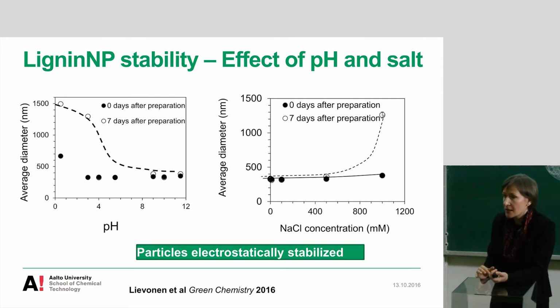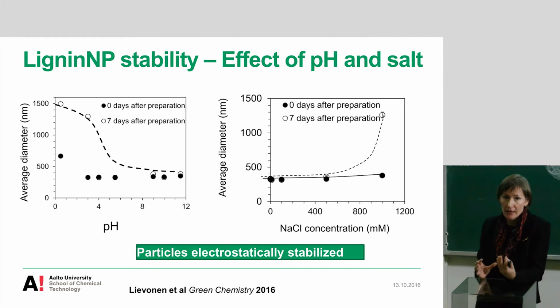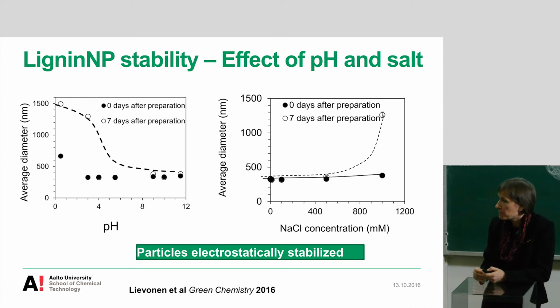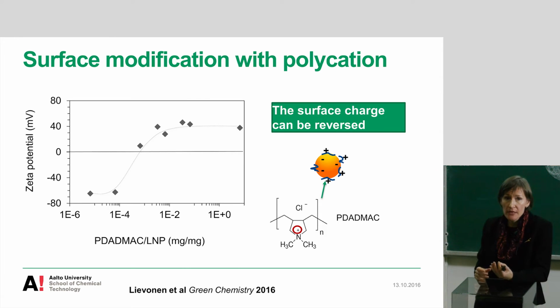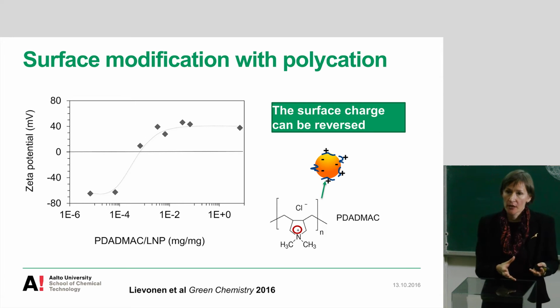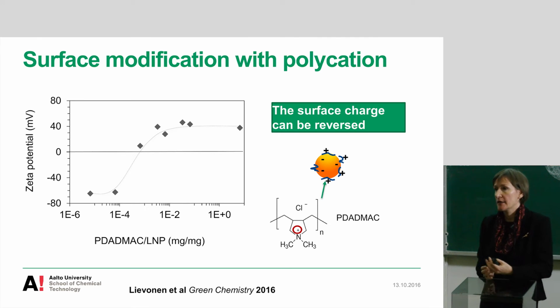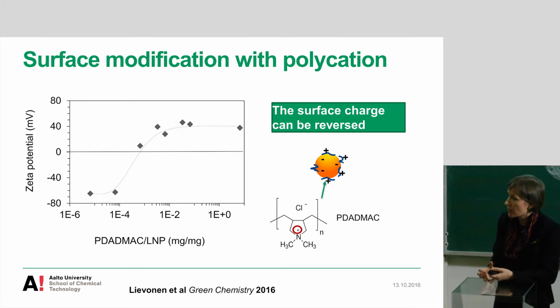They are electrostatically stabilized, that means that they are charged, and in aqueous media they stay well dispersed due to this charge. We can modify their surface. We have done it by adding a cationic polymer, so we can go from the anionic charged particles to cationic particles. And we can adsorb many different things other than this polymer. We have adsorbed proteins to make it more applicable in different applications.